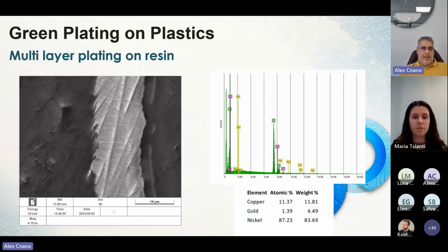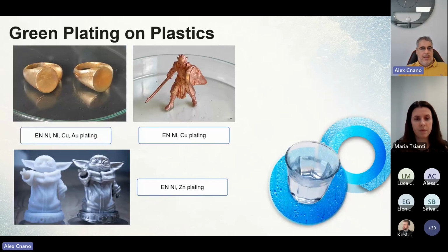We can see here with some images and EDS analysis the level of the adhesion. Here we have the substrate, the coating, and the embedding resin. You can see that we can have an excellent anchoring of the coating in the substrate using such technologies and different types of coatings. Here you can see the final object. We have some rings that started with electroless nickel, a nickel type of bath, copper, and a final top coating of gold, and of course copper plated or zinc plated.